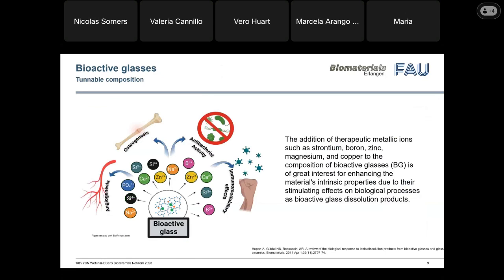Okay, so we have seen that bioactive glasses are versatile materials, and this is due to the possibility to design their composition according to the functionality we want. This is done by incorporating therapeutic ions such as strontium, copper, zinc, magnesium, boron, which will have an effect not only on the glass properties, but also lead to different biological responses. For example, if we want to have an antibacterial effect, then we could add zinc or copper. But if we are interested in stimulating the formation of new blood vessels, then we consider, for example, boron.